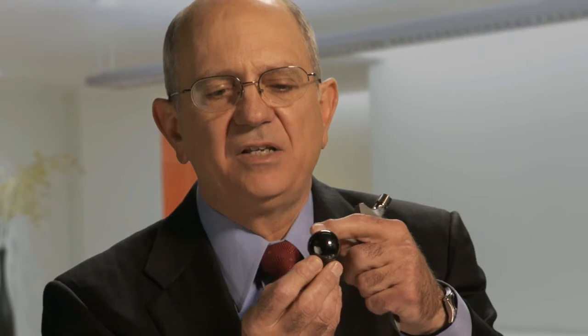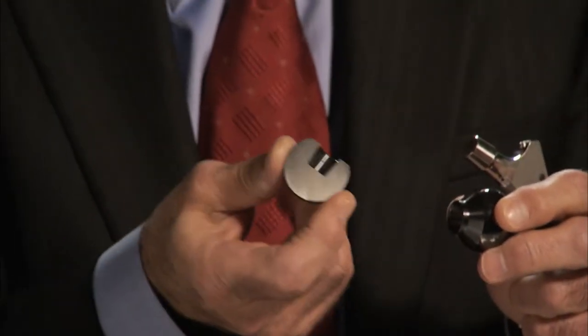Here is another advance: the use of metal oxinium, which is a transition metal with a surface that is ceramic in nature but an inner core that is metallic. This eliminates the risk of fracture associated with ceramic. We can also see here an example of highly cross-linked polyethylene material, which is subject to ionizing radiation in an inert gas environment, resulting in the virtual elimination of wear at the surface.